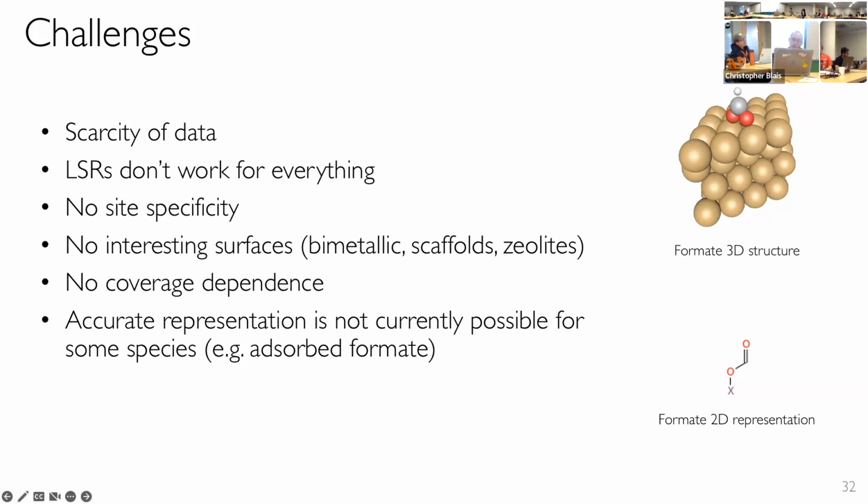So this is formate, which is an important molecule in a number of mechanisms, such as methanol synthesis. It forms this bidentate structure, but with our bond order preservation when we're constructing these species, we can't have 2 oxygen atoms bound to the surface and also bound to that central carbon in a bidentate formation.